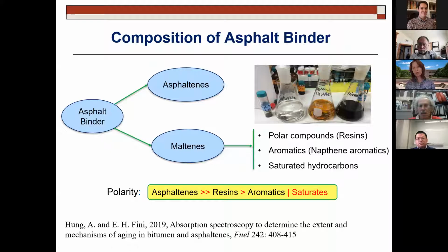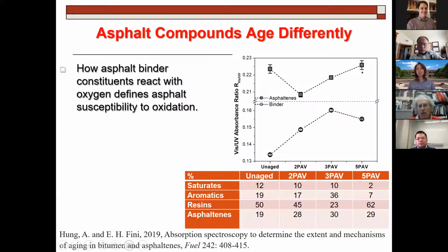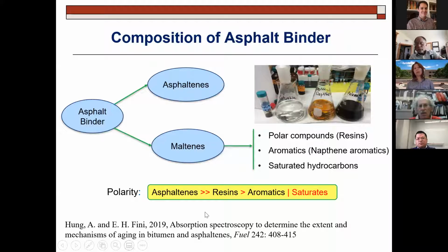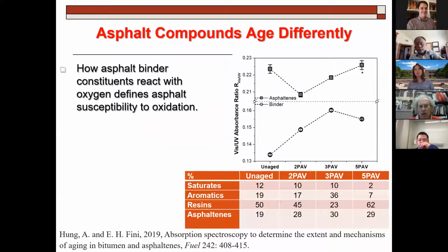So when I talk about carbons, carbons are in these elements. They're embedded in these molecules. If you think about the polarity of them, asphaltene has the highest polarity, followed by resin, followed by aromatics, and then finally saturates. Why am I showing you the polarity? Because the more polarizable material is more prone to oxidation. And why am I talking about oxidation? Because oxidation is causing aging, which we don't want to happen.